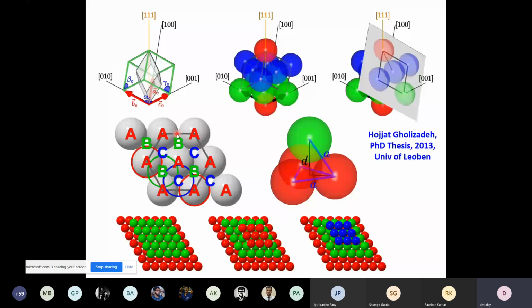So sometimes when phase transformation occurs, when HCP martensite forms from austenite, it occurs by deformation. Deformation not only increases the energy of austenite, increasing the MS temperature to MD, but it also creates nuclei for HCP martensite.